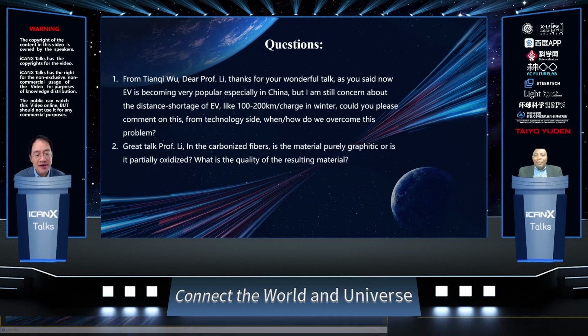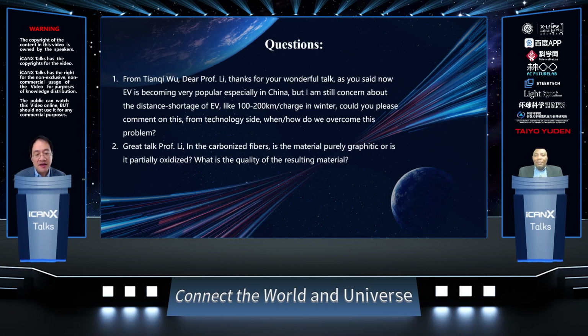That's a great question. So in fact, if it's purely graphitic, it doesn't work. So those carbon nanofibers always have some oxygen, some sulfur, some hydrogen, some of these groups on the surface. And what we found was actually the more dirty it is, the better dispersive power we get.